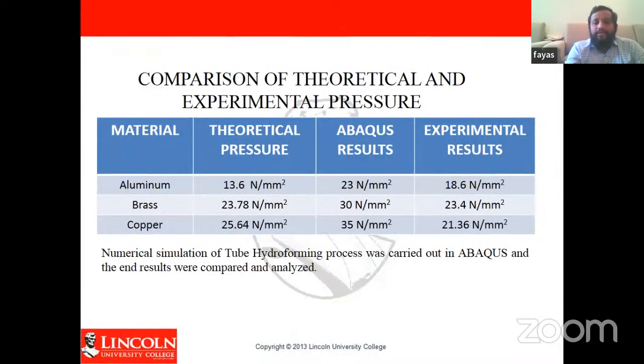And then we compared all the things. Theoretical pressure is 13.6, 23, 25 for aluminum, brass, copper. Abaqus result is 23, 30, 35. Experimental result is 18, 23, and 21. So all the numerical simulation was conducted in Abaqus and compared with theoretical, and all are quite reliable.